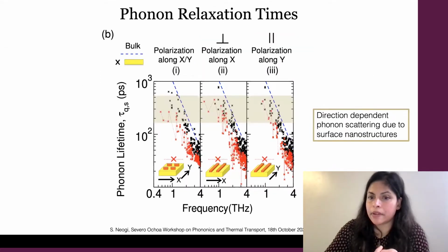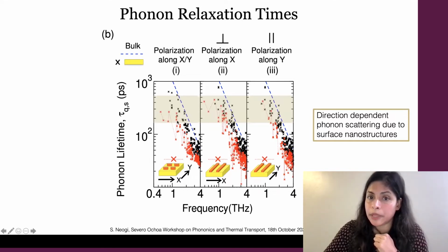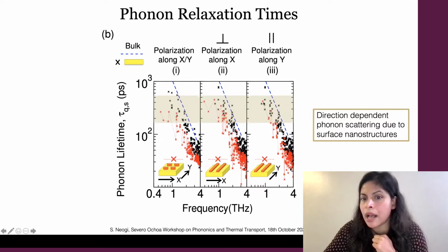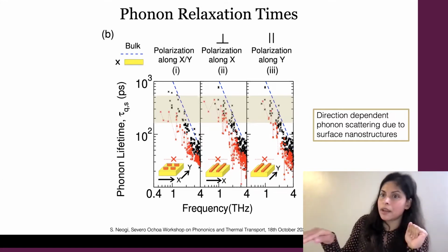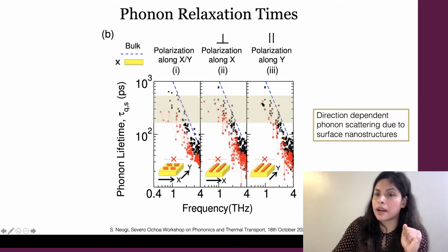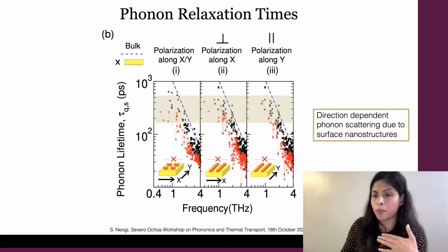We also calculated the relaxation time. These are very, very heavy calculations because these are around 5,000 atoms. And we saw a little bit of anisotropy there too. What is interesting is that the low frequency relaxation time becomes almost flat over here. Although we don't have as much sampling because the sample size is pretty small, along the perpendicular direction you have a flattened relaxation time, but here you do not see that flatness. So we can see something anisotropic happening from this viewpoint as well.